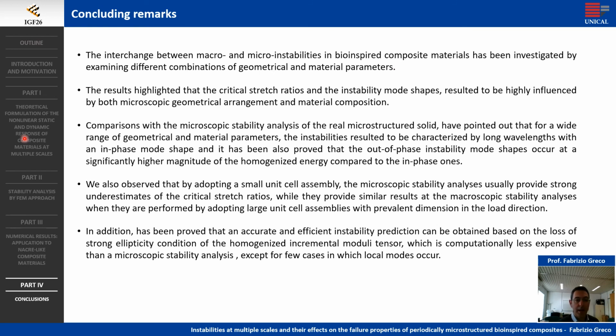In conclusion, the results highlight that the critical stretch ratio and the instability mode shapes are highly influenced by both microscopic geometric arrangement and material composition. Comparison with the microscopic stability analysis of the real microstructured solid has pointed out that for a wide range of geometrical and material parameters, the instabilities resulted to be characterized by long wavelengths with an in-phase mode shape. We also observed that by adopting small unit cell assemblies, the microscopic stability analysis is able to provide strong underestimates of the critical stretch ratio, while they provide similar results with respect to the macroscopic stability analysis when they are performed by adopting very large unit cell assemblies with prevalent dimension in the load direction.